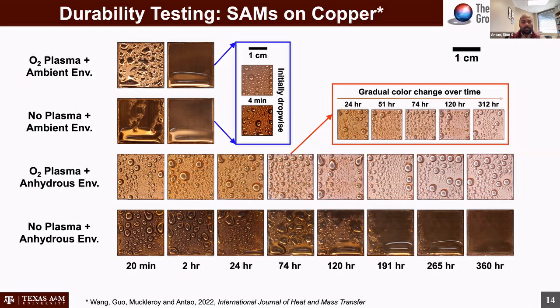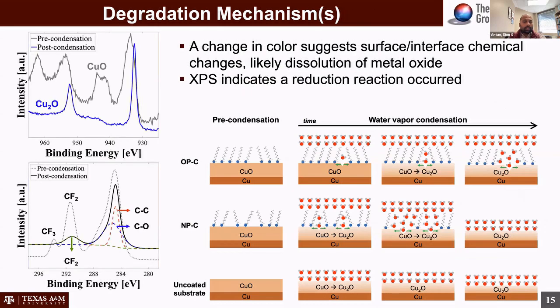But as I'll talk about in the next slide, I think it's some level of a chemical reaction that's changing the oxide nature just below the silane coating. And if you look at the XPS data, it actually shows you that we are transitioning pre-condensation from a cupric oxide surface to a cuprous oxide surface. And we believe this cuprous oxide surface is more soluble than the cupric oxide, though there's not a lot of evidence either way in the chemistry literature on the solubility of one versus the other.